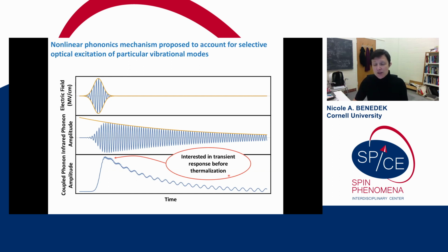The rationale for saying that is that, if you look at this mechanism, if the ringing IR mode creates a force on these coupled modes that causes them to displace, then when the IR mode gets damped, the coupled modes should also ring down.